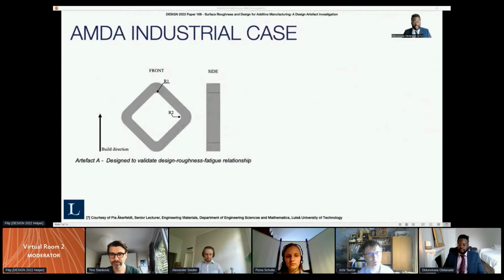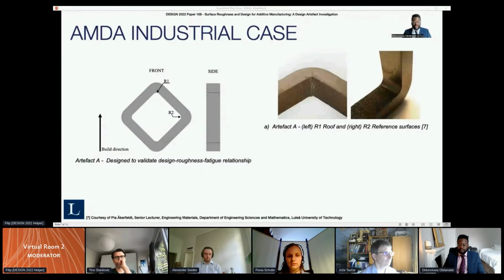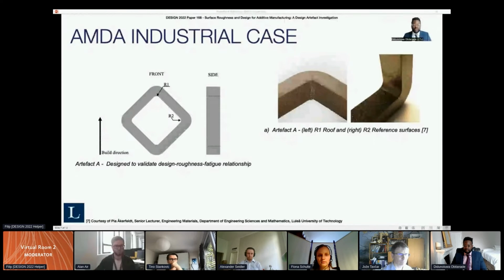This artifact, Artefact A, was designed to resemble the internal roof geometry of the manifold design, investigating the roof radius at a 4 mm radius, R1, and comparing it to a less rough surface of the same radius, the reference surface, R2, to the right. Shown in Figure A, R1 had a high level of dross formation, creating a much rougher surface compared to that of R2. Also, transversal shrinkage has occurred, indicated by a distortion line at the roof junction layer. 10 A artifacts were produced, and we found that the average R1 radius was 2.7 mm instead of 4, whereas the average for R2 was 3.9.